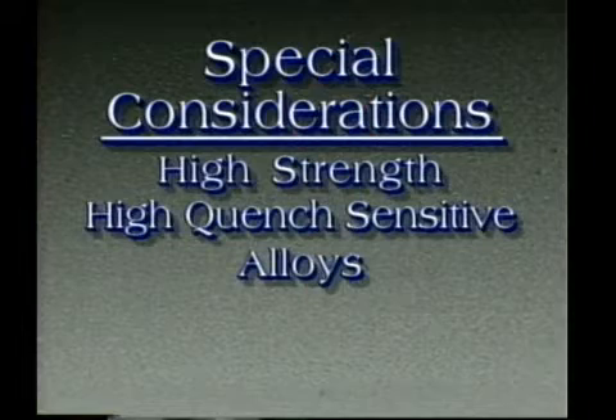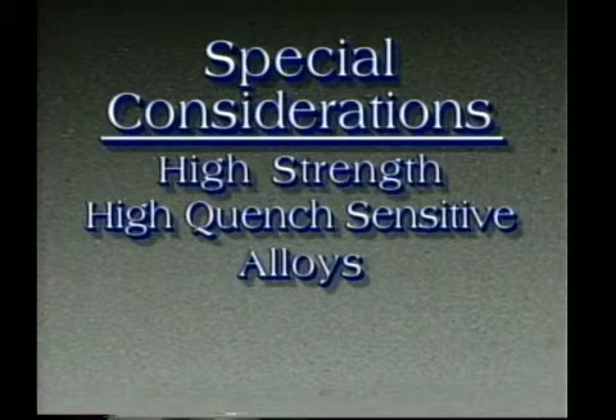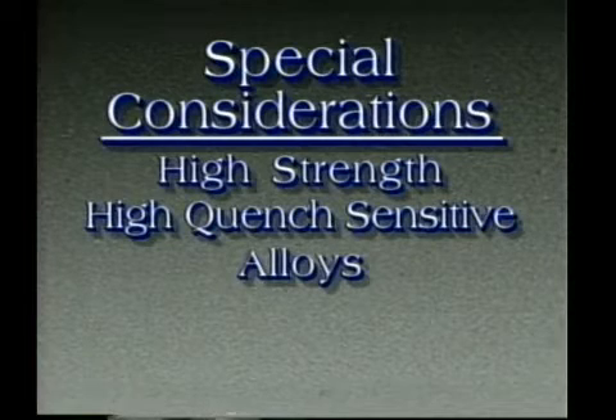Pre-production qualification of the quenching procedure, including both destructive and non-destructive testing of heat-treated parts, should be performed before a spray technique is used. Once the technique is established, it must be rigidly followed regarding racking, placement of nozzles, and pressure of the spray. Also, rigid maintenance procedures must be followed to ensure that nozzles do not get plugged or corroded.